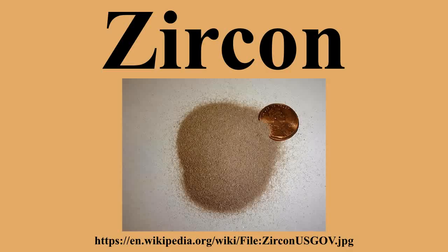The color of zircons can sometimes be changed by heat treatment. Common brown zircons can be transformed into colorless and blue zircons by heating to 800 to 1000 degrees Celsius. In geological settings, the development of pink, red, and purple zircon occurs after hundreds of millions of years. If the crystal has sufficient trace elements to produce color centers, color in this red or pink series is annealed in geological conditions above the temperature of about 350 degrees Celsius.